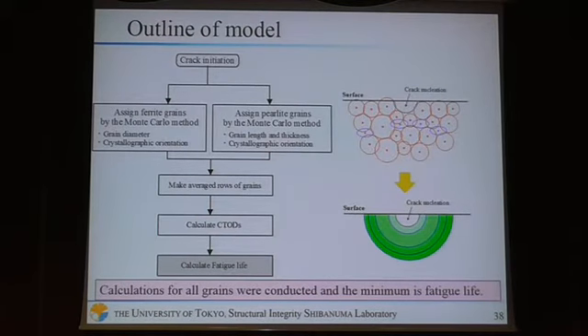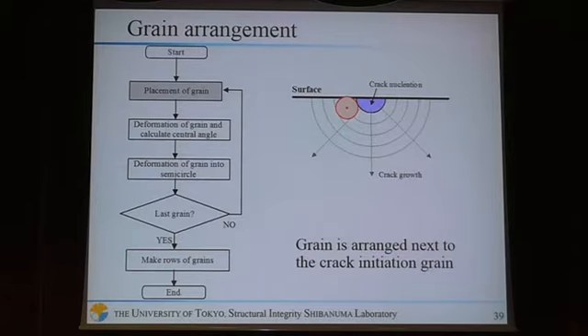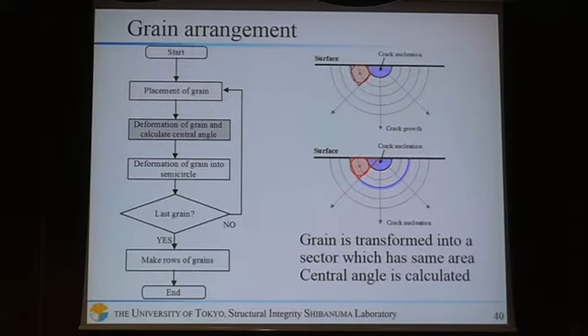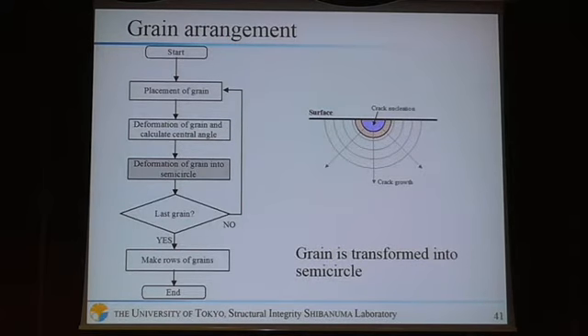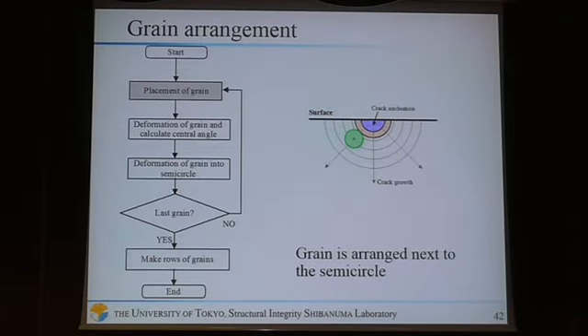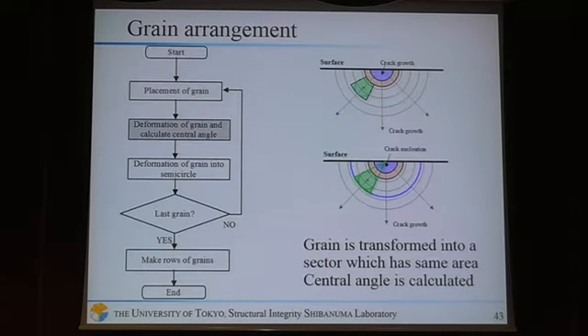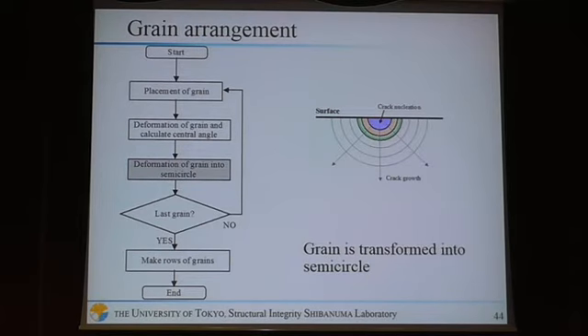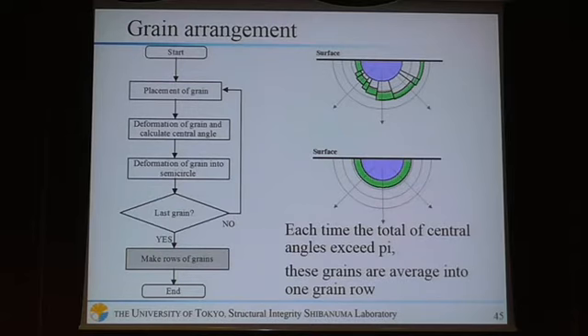Next, I'll talk about this grain arrangement in more detail. First, grains are arranged next to the crack initiation grain. Each grain is transformed into a sector which has the same area, and the central angle is calculated. Next, the grain is transformed into a semicircle. Next, a grain is arranged next to the semicircle. This process is repeated until all grains are arranged. So each time the total of central angles exceeds pi, these grains are averaged into one grain row.